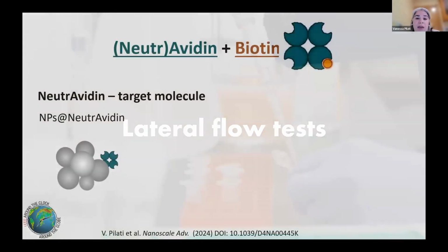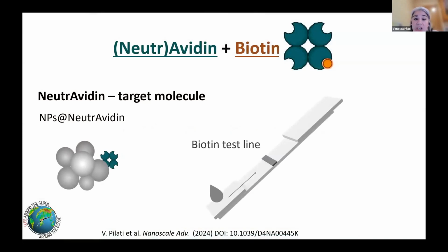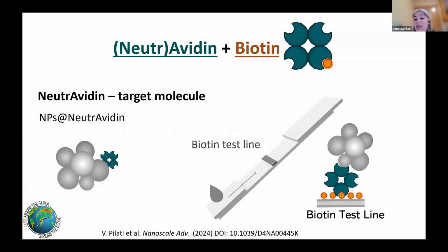So we investigated their performance in lateral flow tests. We used the avidin biotin model as a biorecognition. These are two proteins that have a very strong affinity between the two. So what we did was to attach neutravidin proteins on the surface of the nanoparticle, and we printed a biotin test line, and we put the system to flow in the nitrocellulose membrane. If we have the neutravidin on the surface, these nanoparticles will be captured by the biotin line, and they will provide a color and a magnetic signal that we can detect and quantify.